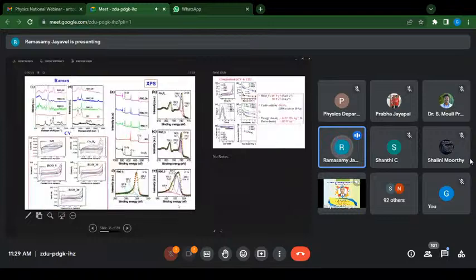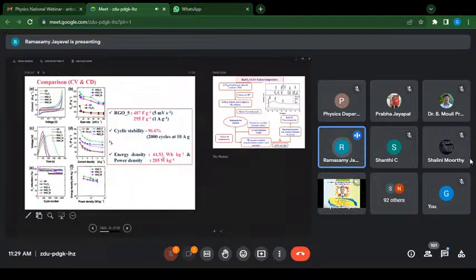So this is actually the electrode fabricated with tin oxide, and this is with cobalt oxide. With the cobalt oxide, they could achieve an energy density of about 44 watt hour per kg, with power densities close to 300 watt per kg. Then we tried with ruthenium oxide, where we could get a current density of the order of ampere range. We started with microampere, then milliampere. Now we achieved ampere range, so that the power density and energy density can be maximum.